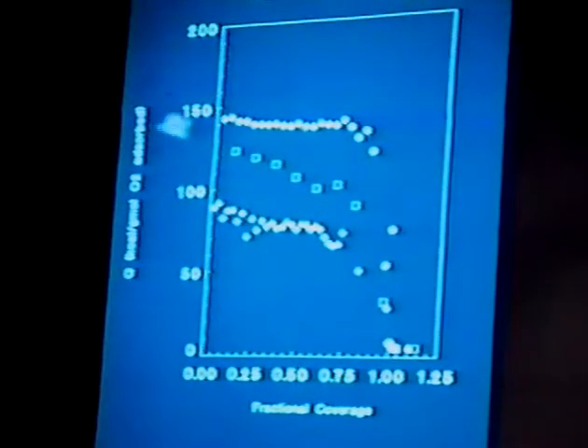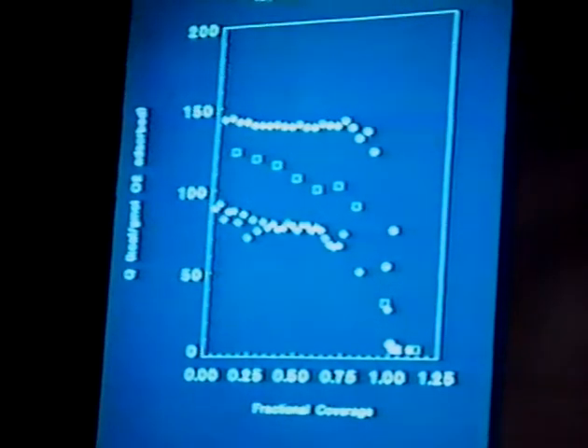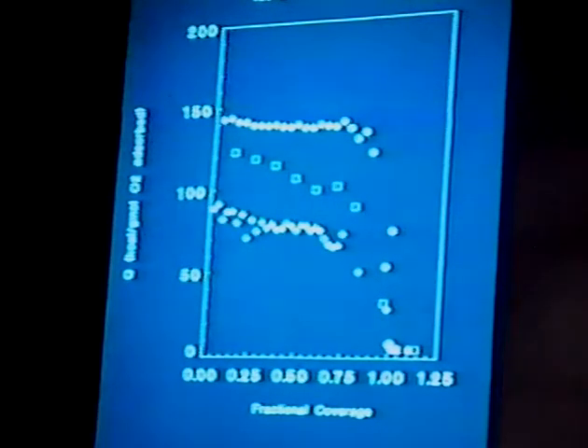Now if we compare these data with the data from oxygen adsorption on the bimetallic sample after the high temperature reduction alloying step, what I've done here is I've normalized everything to correspond with a total oxygen coverage of 1. What you see is, here's that iron data and the rhodium data again. The bimetallic data falls between the two extremes throughout the coverage range. It starts a little higher working towards the iron extreme at low coverage and tends to fall towards the rhodium end at high coverage. But throughout the coverage range, we're looking at adsorption that appears on the basis of this to be oxygen adsorption on a bimetallic surface, a surface that consists of both types of atoms.